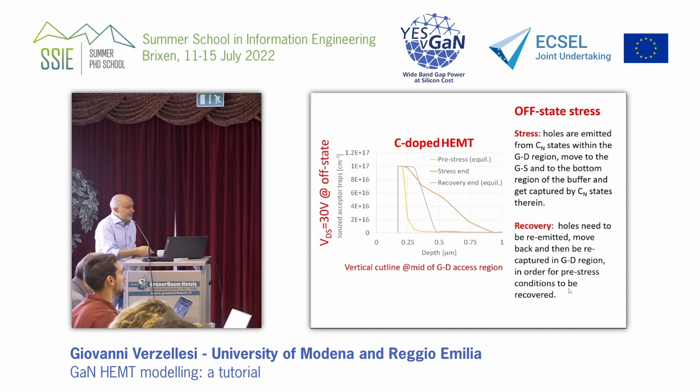And then, okay, during off-state stress, you basically have a picture where the hole redistribution model is able to explain the larger degradation observed in carbon doped devices compared to iron doped devices.